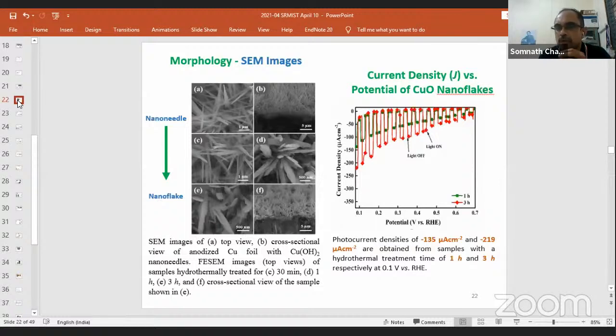We wanted to do some work on copper oxide, but my student, this is the work of my third student, actually found out something: if you take copper oxide as a single crystal in bulk material, you find very pure copper oxide. But if you want to go to copper oxide nanostructures, for example, the nanostructures shown here, nanoneedle, nanoflake kind of thing, then you always have this challenge of having a CuO, Cu2O mixed phase, which resulted in lower than expected photocurrent value. So what is this photocurrent? That is when we are measuring current under light irradiation.